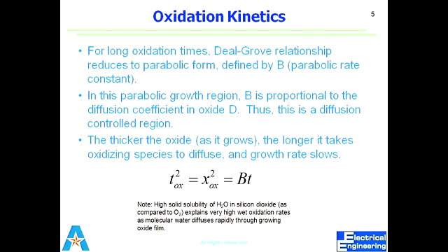It takes much time for the molecules to diffuse through the oxide layer. So that's why we say that when the thickness of the oxide becomes very thick, at that time the reaction rate would get slow due to the diffusion, because it's limited by the diffusion. So we say this is the diffusion controlled region. It was a reaction rate controlled region, and this is a diffusion controlled region. Any question up to here?